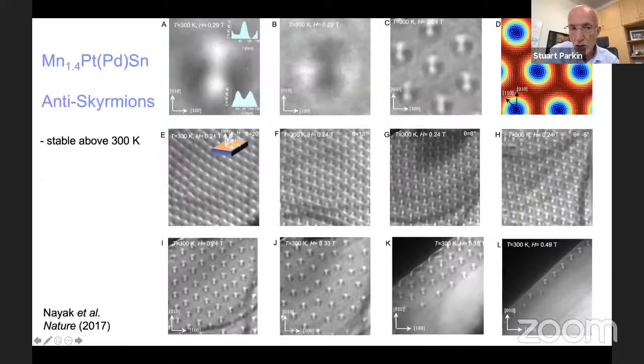So if we now look at a real structure, and here we've taken this manganese 1.4 platinum tin Heusler single crystal from Claudia Felser, we've made a thin layer from it, 100 nanometers thick, by using focused ion beam milling. And here you can see in the top row, number A, this is an image of an anti-skyrmion. This is about 100 nanometers in size. This is at room temperature in the presence of a perpendicular magnetic field. But interestingly, if you look here at C, you can see that you have an array, a hexagonal array of these anti-skyrmions. And this array then will evolve as a function of temperature and field. And the rest of these micrographs show different magnetic fields and how the whole array evolves.